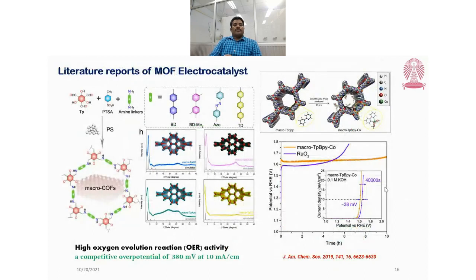So some literature reports of MOF in electrocatalysts. This is a macrocyclic MOF. It can be synthesized from triformylphloroglucinol, para-toluenesulfonic acid, and different types of amine linker in the presence of polystyrene substances. It produced a macrocyclic COF. They can change the linker and get different types of MOF. In this COF, they reacted with cobalt acetate and produced macrocyclic MOF. They evaluated the OER activity of both cobalt and copper, but the cobalt one exhibits higher activity due to the improved porous structure being easily accessible for the active sites.